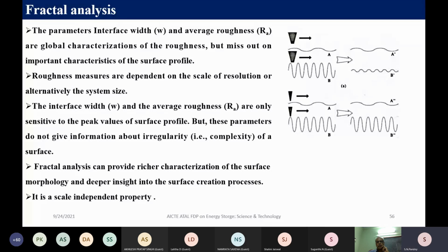So one can see that the parameters, that is interface width and average roughness, are a global characterization of the roughness, but they miss out the surface profile. Although we can measure the interface width and the roughness, the surface profile is missing here. What is the exact surface profile?